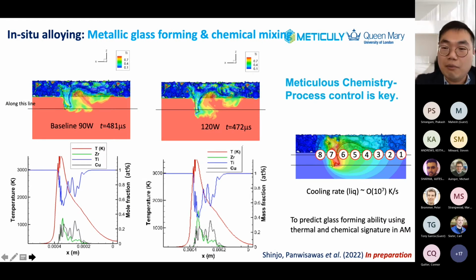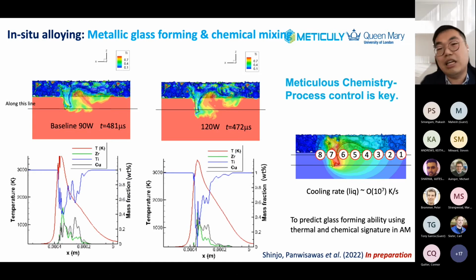So just to give you a bit of flavor of what we can do, we have to meticulously control chemistry and process. And for this one we have a representative process condition, and you will see from the chemistry map, as a result of this high-fidelity model, that there are some differences if you vary the process condition. And this can be quantified and predicted if we use this model. And not only that, we can link further to the solid-state transformation. If we get this right, your thermal signature will be right. And not only that, the trend after this is the chemical signature. We need to get it right as well for additive manufacturing.